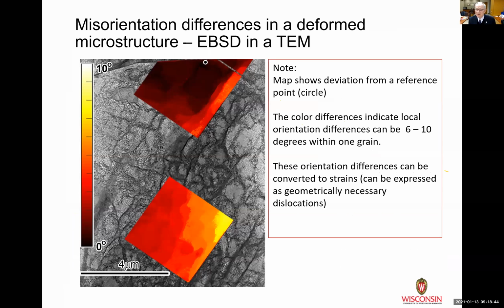We can do other things now too. As I said, as we increase the level of deformation and we make the dislocation structures tighter and tighter, those cell structures get smaller and smaller, the next thing that must happen is you'll get local rotations. Just think of trying to deform something. It's going to try and deform. It can also rotate to take into account that deformation. Each of the cells will rotate slightly differently. It makes perfect sense when you think that's what's going to happen inside a material. But can you measure it?